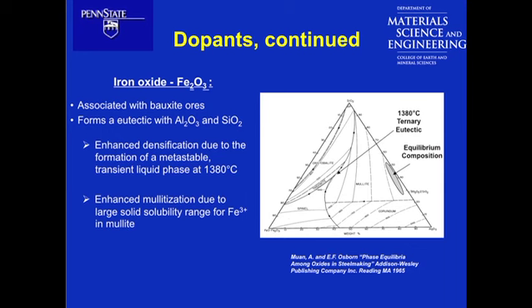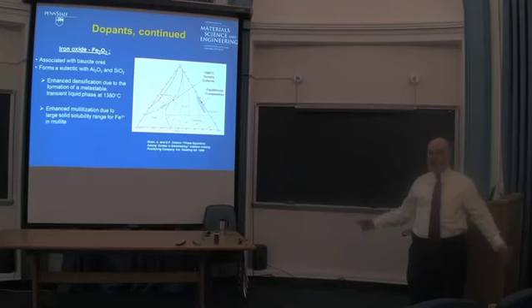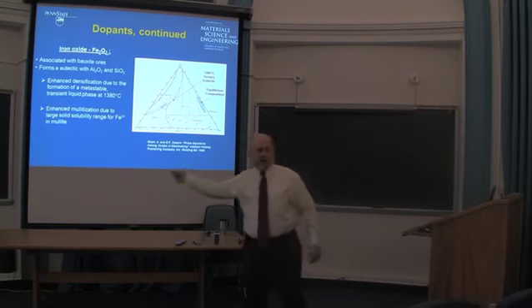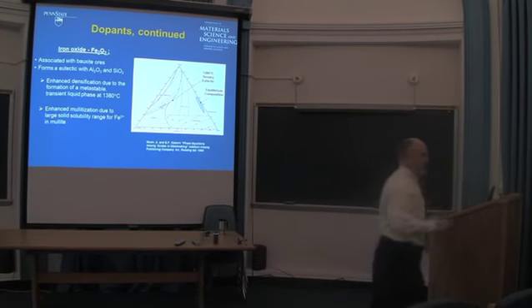Iron oxide, why? Iron has several different valences. You sat through Stubbe's course. Do you remember the iron oxide phase diagram and the isobars and the experiment that Tressler made you do in your thermal treatment lab where you made an iron oxide pellet and you put it in a gas-fired furnace and you heated it up and you changed the PO2 and all of a sudden it went into a puddle? Changing the valence of the iron in an iron oxide alters its melting point.